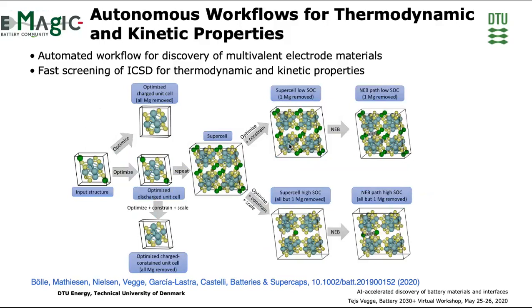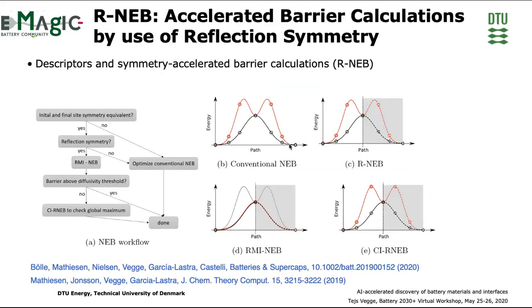And then depending on the material symmetries and the kind of transport barriers you detect, you can then run only the minimum level of kinetic analysis that's needed. If the electrode material has a reflection symmetry, you only need to calculate the energy of the structure at the mirror image. If that's above a certain threshold, you know that that material will not be kinetically relevant and you don't have to look more at it. If it's lower or it has a broken symmetry, you need to use more complicated methods.